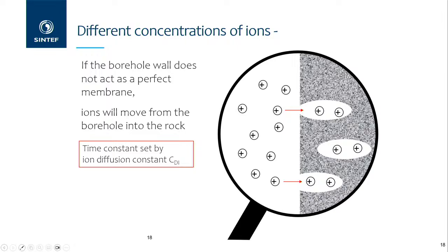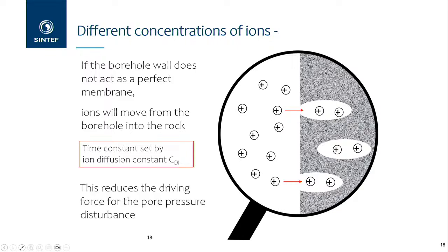At the same time, we know from many experiments that shale is not a perfect membrane. If it were perfect, the membrane efficiency, a parameter on the next slide, would be 1, meaning it only allows water, nothing else. But shale is a leaky semi-permeable membrane. So not only water is moving, but also a little bit of ion will start to move in. This ion movement is governed by the ionic diffusion constant, which dictates the movement depending on the concentration and the types of ion. If that happens, the gradient that you created by exposing two fluids of different ionic concentration will diminish, right? So with time, the pressure gradient will go away.